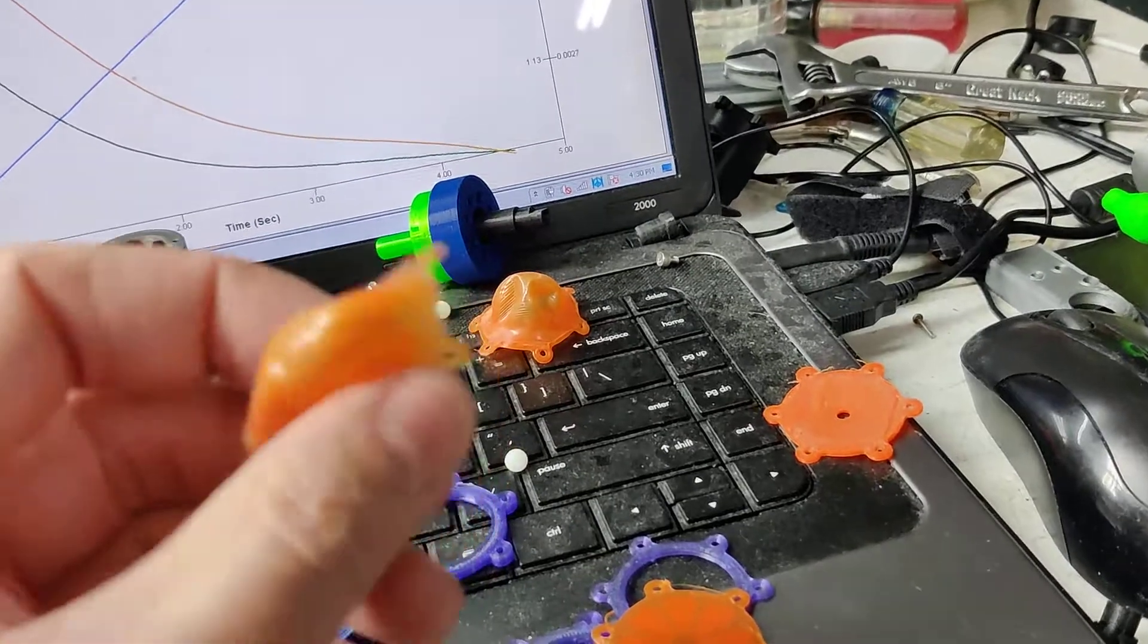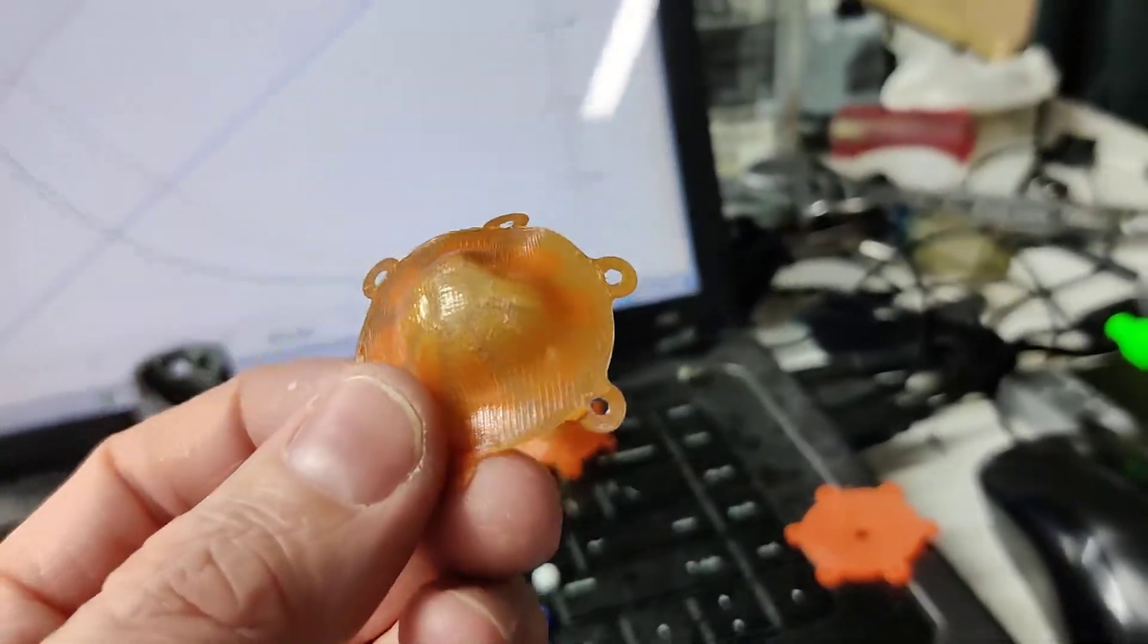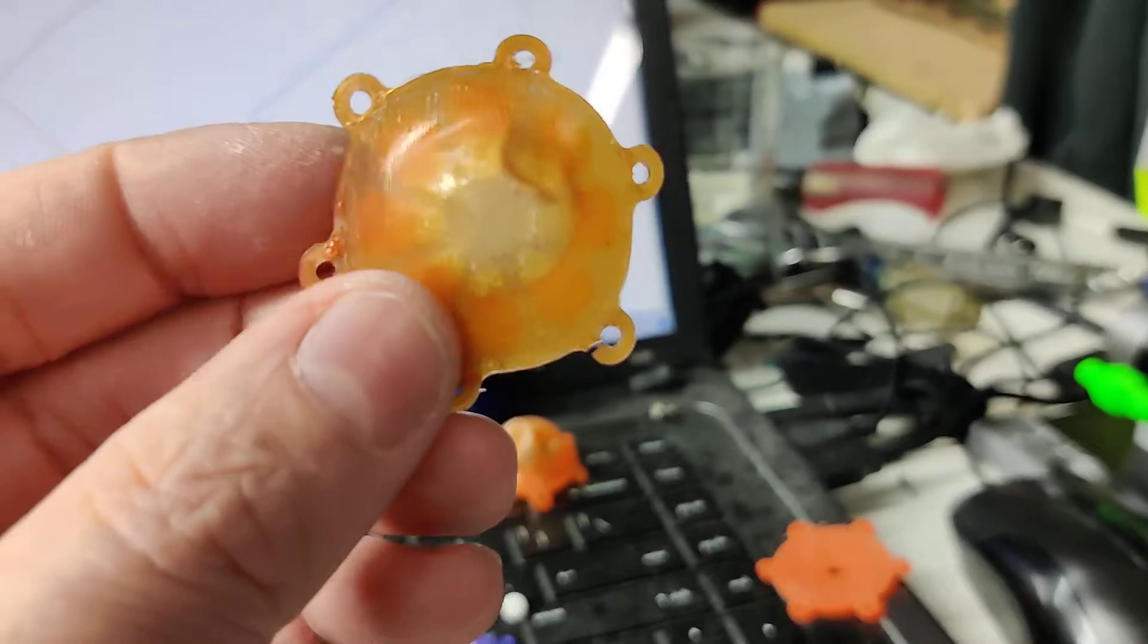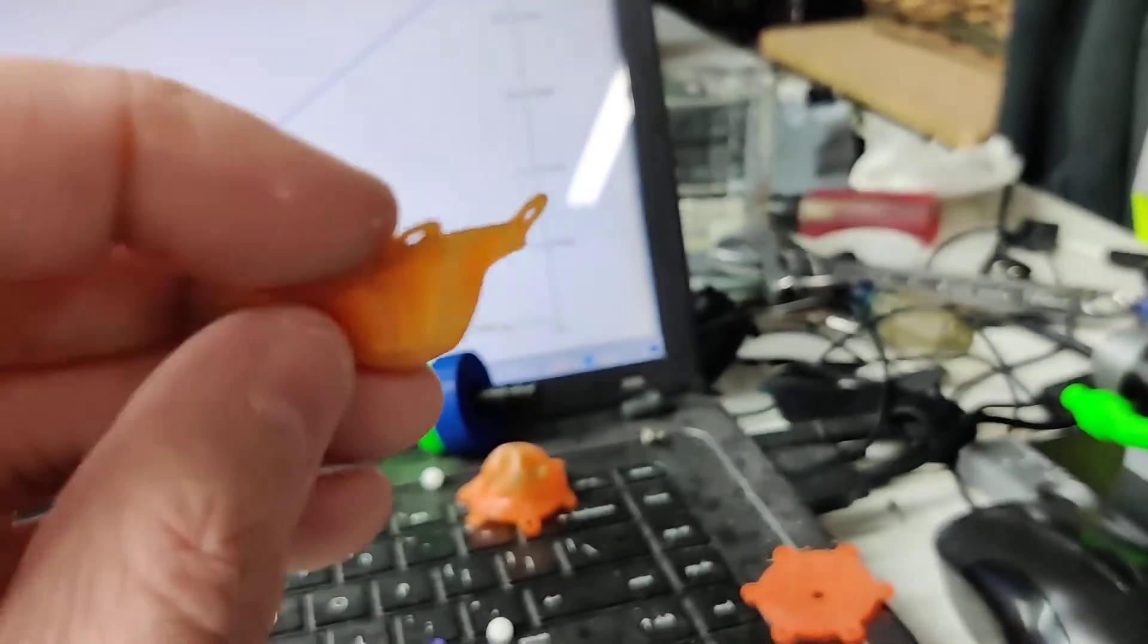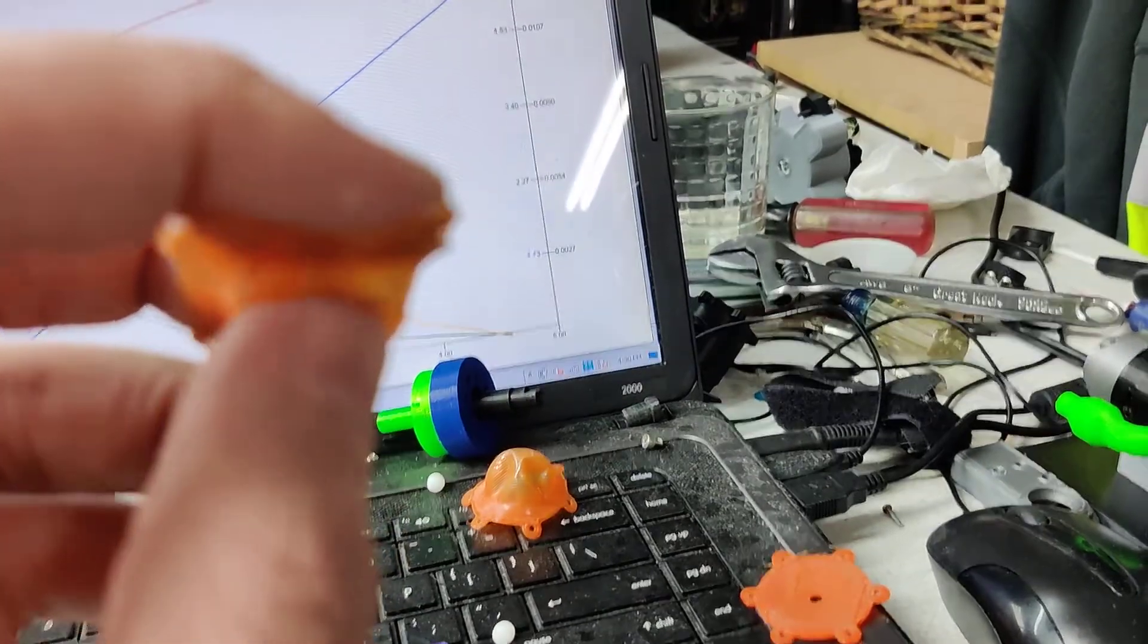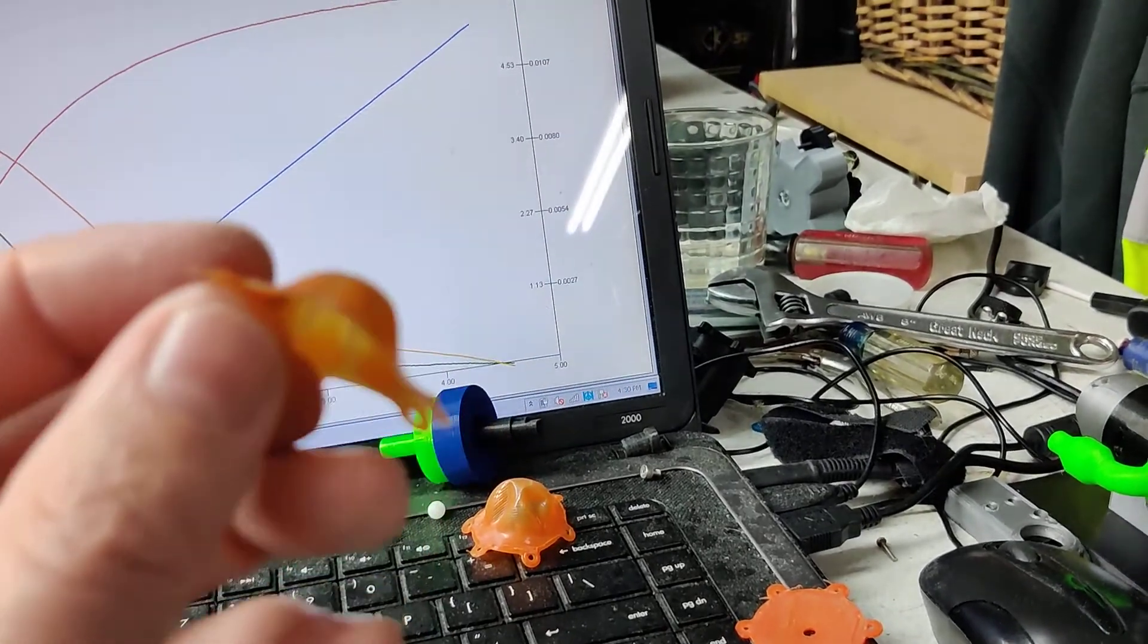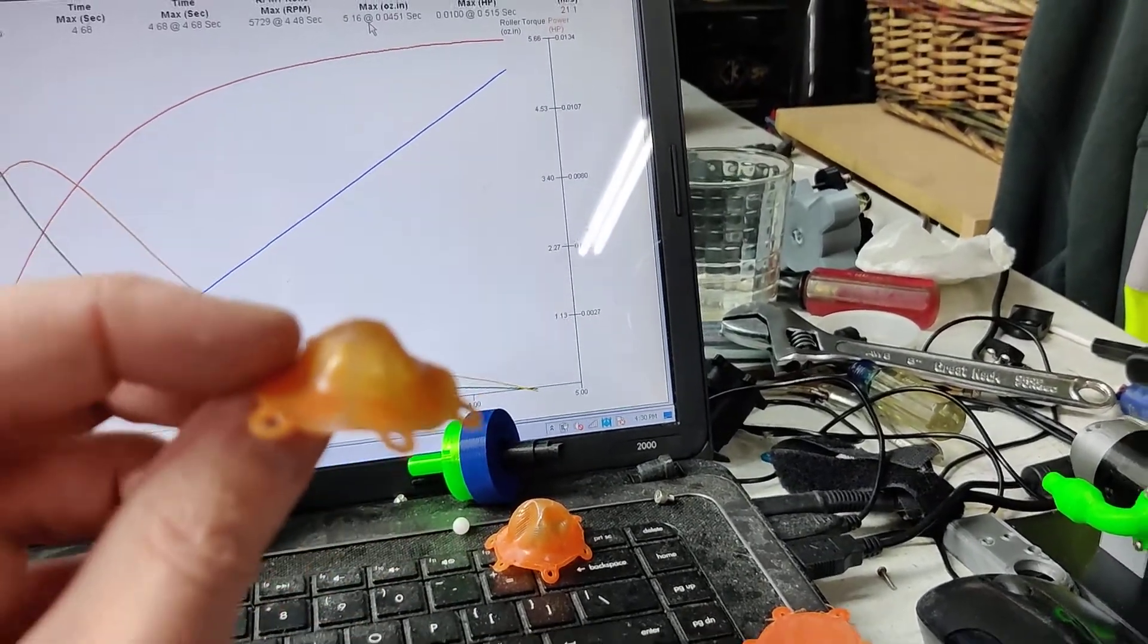This one deformed this bad at around 60 PSI and it's twice as thick. So this one's half the thickness, same PSI, that's all it deformed to which this is an acceptable amount of deformation because the piston is going to push this back up as it comes up into the stroke and then it's going to be able to fill that up. So that's a pretty big stroke.